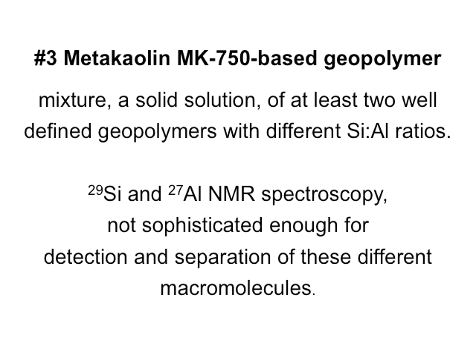We have seen that the result of the reaction with metakaolin is what we call a solid solution. It is a mixture of well-defined geopolymers with different Si/Al ratios, and so far nuclear magnetic resonance spectroscopy is unable to separate the two or the three or the four that constitute this solid solution. The only way is to heat up the material and wait until they crystallize, and then we get nepheline-type framework, calcite-type framework, leucite-type framework, and so forth. So we have to develop and invent a new way of detecting these phases more precisely.